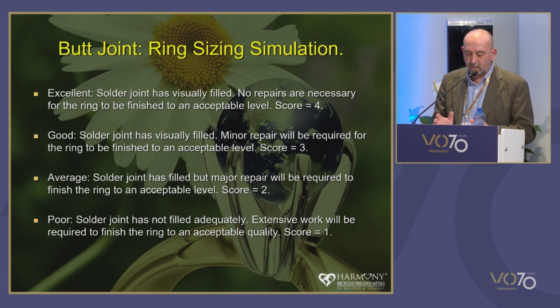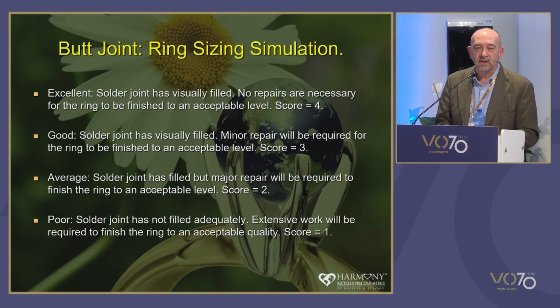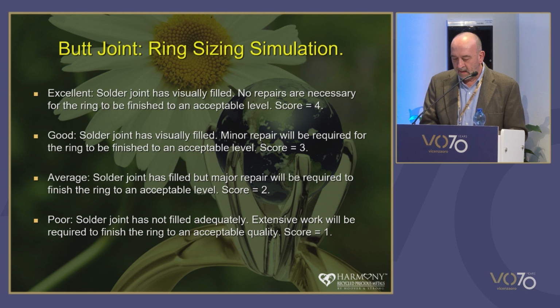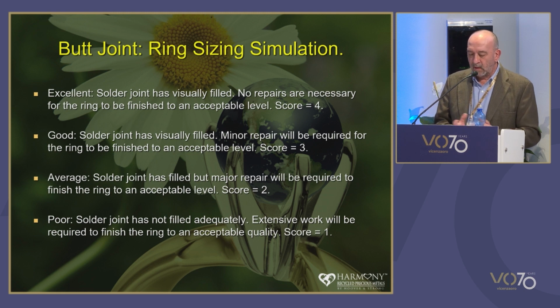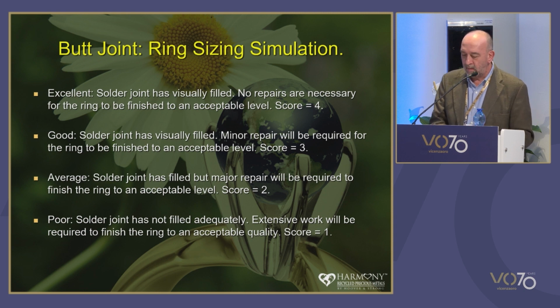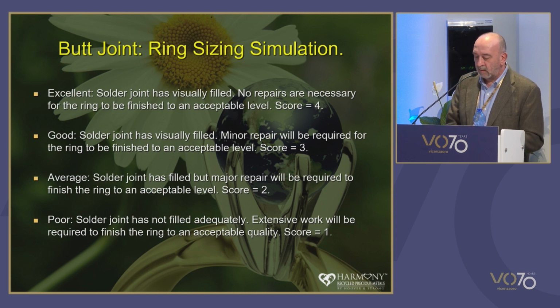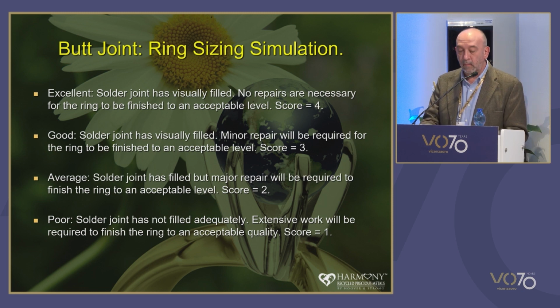We called the solder joint excellent if it was filled and we didn't need to do any repairs to the ring for it to be finished to an acceptable standard, and we scored it 4 points. We called it good if the solder joint had filled, but it needed minor repair, and so we gave it 3 points. We called it average if the joint was filled, but it needed major repair, and we scored it 2 points. And we called it poor if the joint had not filled enough and extensive work was needed, and we only scored it 1 point.